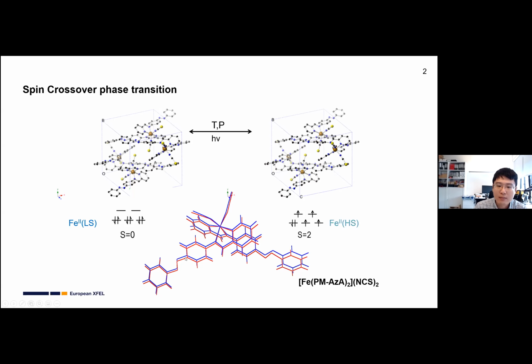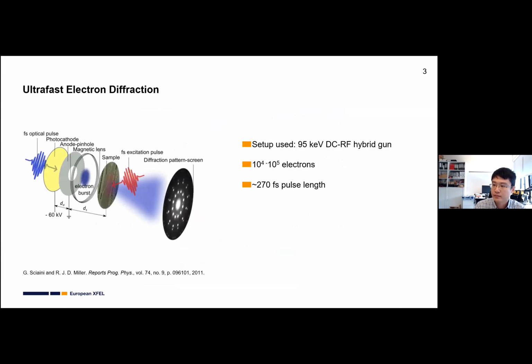After Fe(II) compounds absorb the light, the ground state changes to the high spin excited state by two paired electrons entering the anti-bonding orbitals as unpaired electrons. Therefore, the iron-nitrogen coordination bonds are getting weaker, and we see around 0.2 angstrom iron-nitrogen bond elongation. Also, let me introduce the method I use to study this structure change.